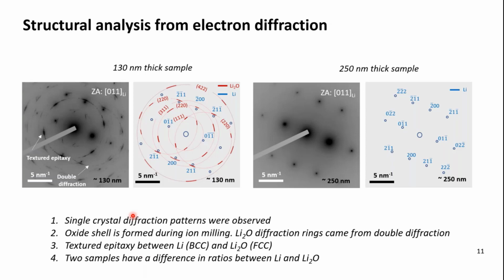I first performed structure analysis using electron diffraction, and what was interesting to me was that they both preserve mainly the single crystal form of lithium. When you look at the diffraction pattern, regardless of thickness, this means the ion beam does not significantly deform the crystal structure of lithium. However, when you look at the thin sample on the left, you can see clear polycrystalline diffraction rings that can be assigned to double diffraction of lithium oxide. We can also see a six-fold symmetry of lithium oxide patterns, which arises from the texture epitaxy between the lithium and lithium oxide. This texture epitaxy can be seen from the interface between BCC and FCC structures.